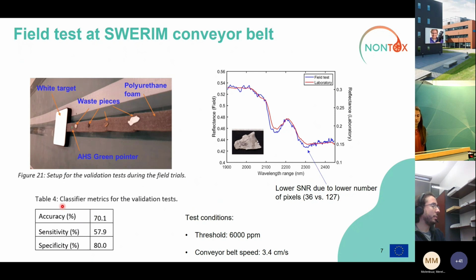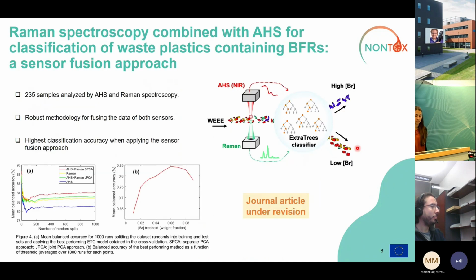And we can see here some metrics of the classifier that we acquired. So you see the accuracy is lower than in the lab, but it's still pretty high. And here is just a comparison of the signal, how it looks in the field test and in the lab for one plastic piece. And it's also showing that it's similar. So the conclusion is that we can apply this sensor in the actual environment.